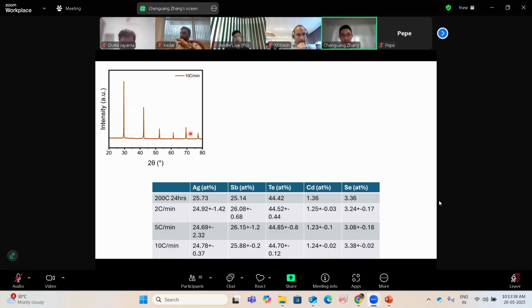As you see, this peak is not very obvious. So probably for this kind of sample, we still need to give it a slow scan to show the small peaks. Let's see if it's silver 2 tellurium, or the silver 5 tellurium 3 or something like that.